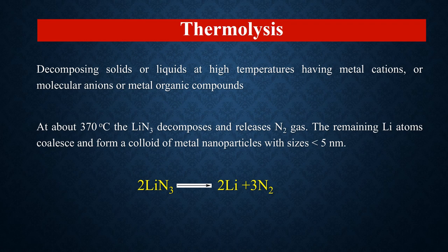There is thermolysis — breaking by using temperature — that is, decomposing solids or liquids at high temperatures having metal cations, molecular anions, or metal-organic compounds. For example, lithium azide when heated at 370°C releases nitrogen and the remaining mass forms lithium nanoparticles. The lithium atoms are initially formed and then coagulate to form colloidal lithium nanoparticles. By this method, very small nanoparticles of less than 5 nm can be obtained.